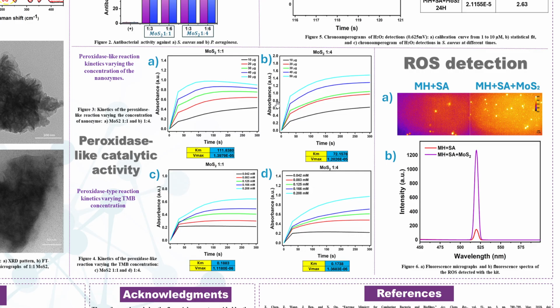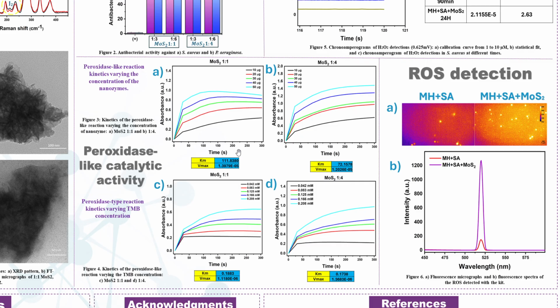We additionally performed kinetic analysis to obtain parameters such as the apparent Michaelis-Menten constant and maximum reaction velocity. Interestingly, we observed differences between the 1 to 1 and 1 to 4 molybdenum disulfide samples. This suggests that modifying the precursor ratio during the synthesis can influence the catalytic properties of the resulting nanozymes, probably through changes in the structure, morphology, and availability of catalytic sites.